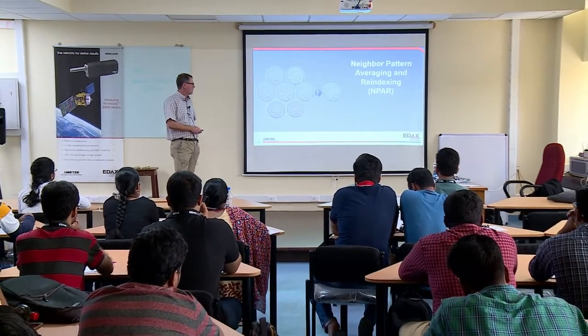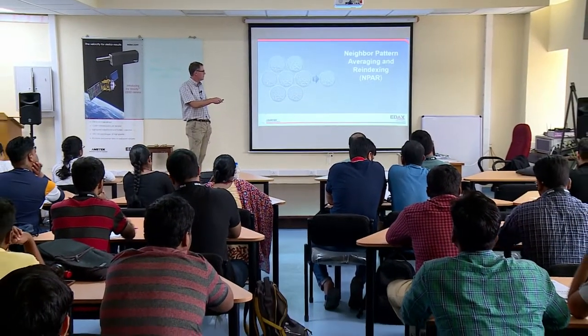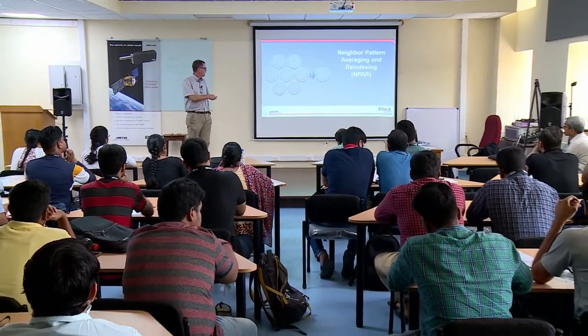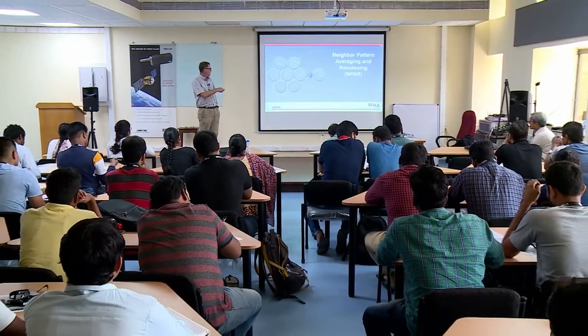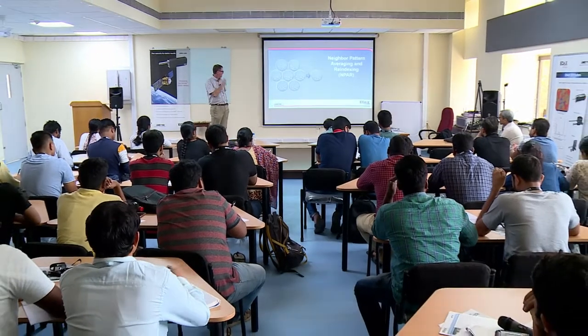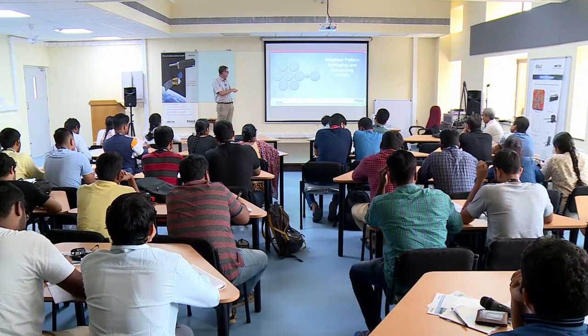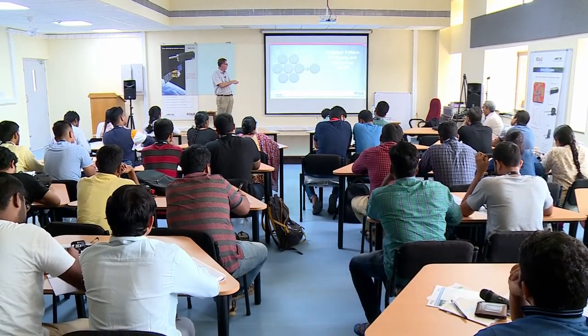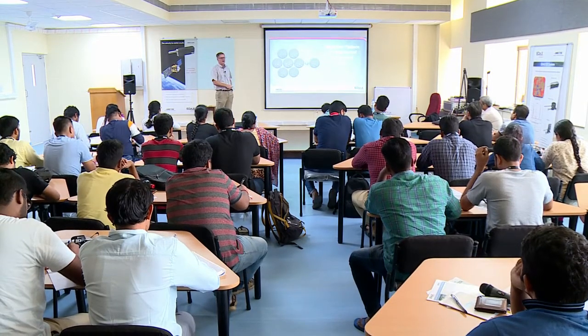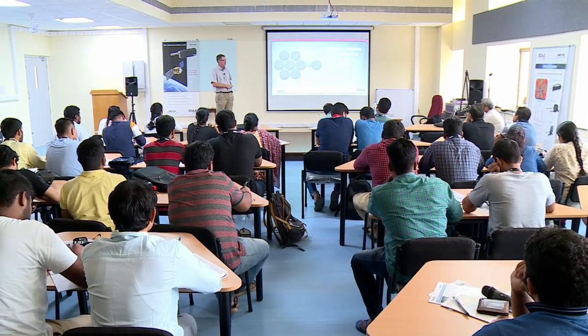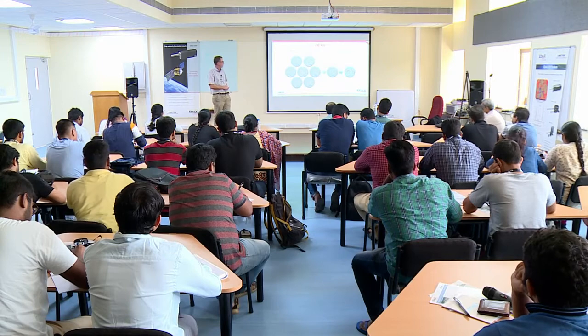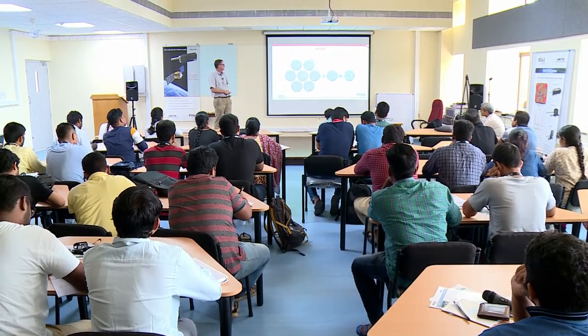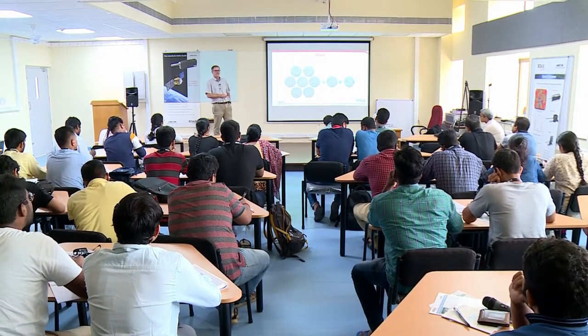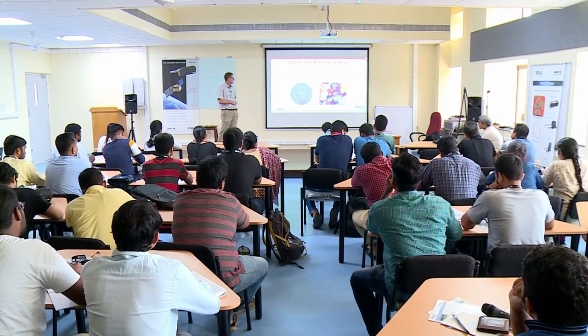So we call this NPAR, Neighbor Pattern Averaging and Reindexing. The idea here is I have a pattern from a pixel, and I take the pattern from all the neighboring pixels and sum them together, and I get an average pattern for that. And it's a little better pattern, typically. And then I re-index it. So this does require that I save all the patterns during scanning.